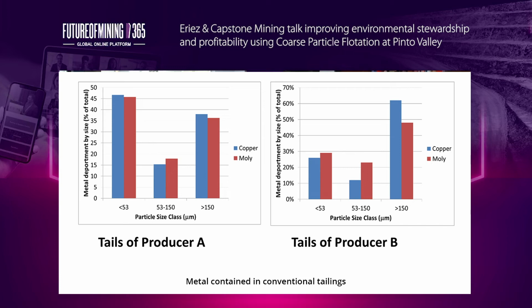But for now, we'll focus on the HydroFloat, which our experience indicates can capture at least 60% of coarse tails. This is the business case for the tail scavenging application: waste recovery, in addition to coarsening the grind of the mill, which allows more tons to be processed. And that's been recently reported by Newcrest for their Cadia Valley HydroFloat application.